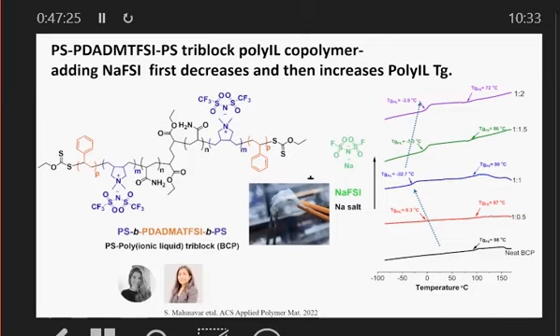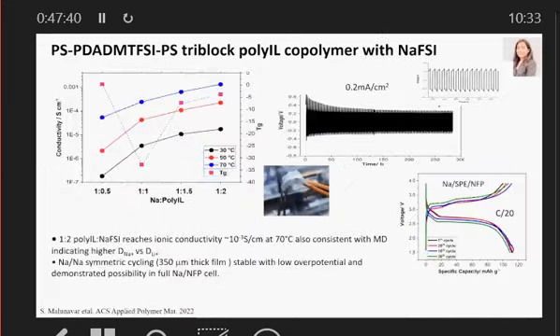What this should do is not move. This should be an ionophobic block. It should not dissolve any sodium salt. It should not decrease the Tg, but it did decrease, and we think that's because it's a small molecular weight group. That means that we couldn't go above 70 degrees without losing mechanical properties. Here we see that conductivity at the 1:2 composition is almost into the 10^-3, which is a factor of 10 higher than the lithium salt, as we saw earlier on, because the diffusivity of the sodium is higher. And again, she was able to show in symmetric cell cycling quite low overpotentials, very stable.